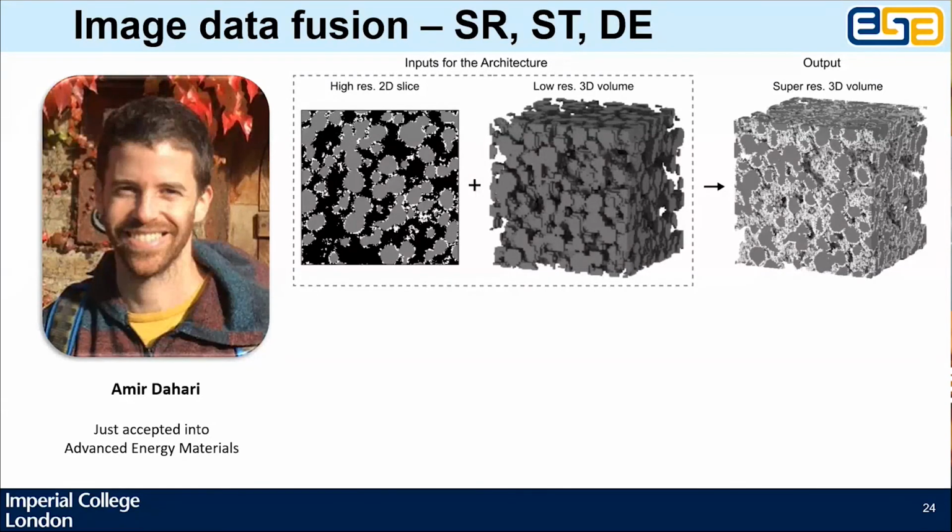And there's another downside of the X-ray data for battery electrodes, which is that essentially the carbon binder domain is invisible, right? And I think there's quite a lot of X-ray papers where they talk as if they can see the carbon binder domain, but they very rarely actually publish the raw projections and the raw reconstructions. And this I don't feel to be the case. I've never seen an X-ray paper where carbon binder domain is convincingly resolved. However, you do in principle have all the information that you'd like.